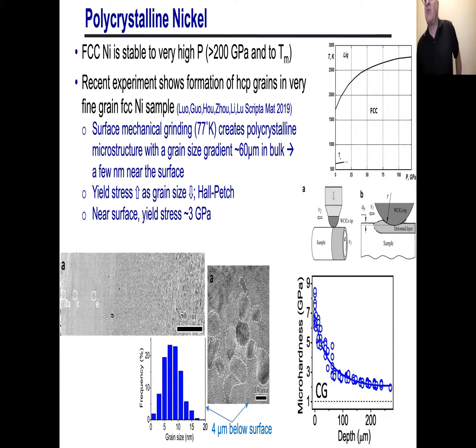And they also went in and did microhardness measurements. And when they did the microhardness measurements, they find as they get closer and closer to the surface, where the grain size is small, the microhardness goes up, with values up to close to 9 GPa. Okay? And it's not surprising that as you go to smaller and smaller grain sizes, you get larger and larger strengths or hardnesses. And if I make the argument that hardness and yield strength are a factor of 3 apart, which is very hand-waving, that suggests that the material there has a yield strength of around 3 GPa, corresponding to the 9 GPa of the microhardness. Okay, well, so that's interesting.